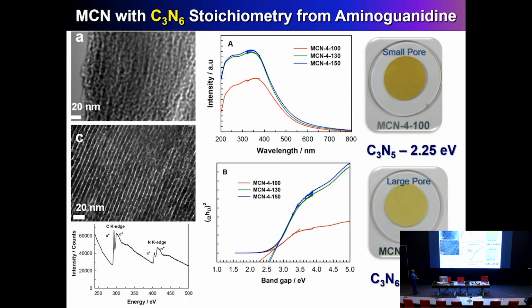And see, when you have a small pore diameter, the decomposition of this material is quite high. But in the case of the large pore diameter, the molecular weight of the polymer that is formed is quite big, and it is very difficult to decompose. As a result, you get the material with a high nitrogen content, and that also changes the band gap of this material. And this is not the only way. So you can change the carbon nitride material by changing the chemistry.